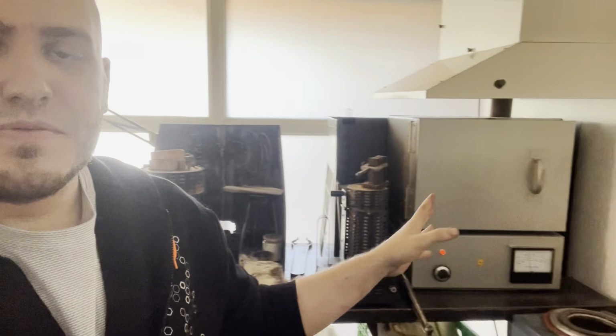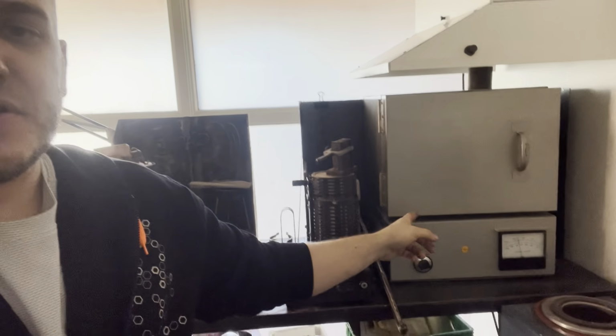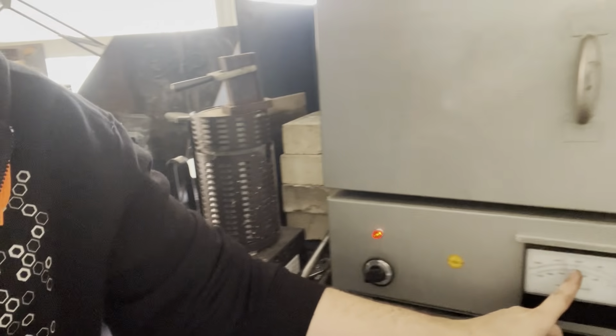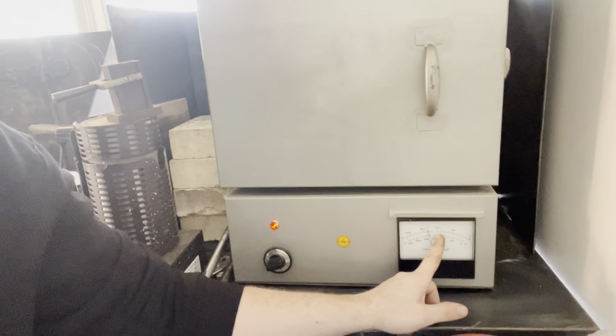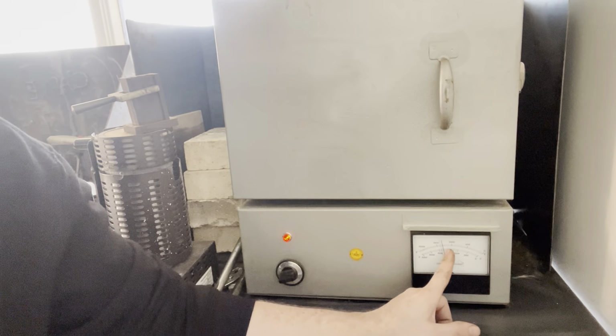Something to note, if you're ever doing a burnout like this with a kiln, preheat your kiln to pretty much as high as you can, because as soon as you load your flasks, I noticed that I had this preheated up to about 1,000, and it dropped all the way down from 600C to 200C. So it was a massive drop. The cold flasks just sucked up so much of the temperature in the kiln that I was left at 200C for like an hour and a half, give or take.